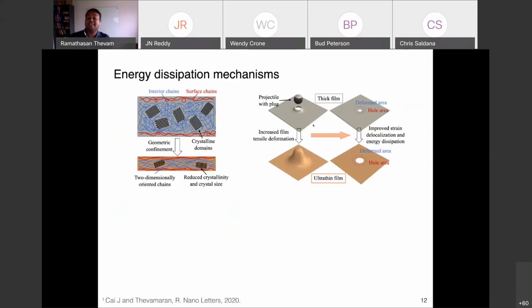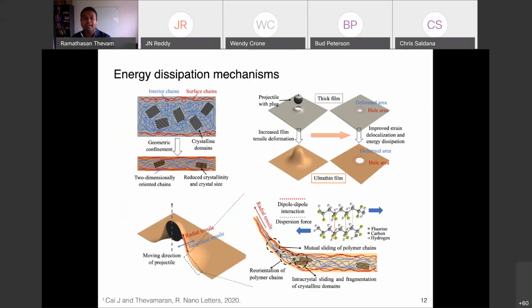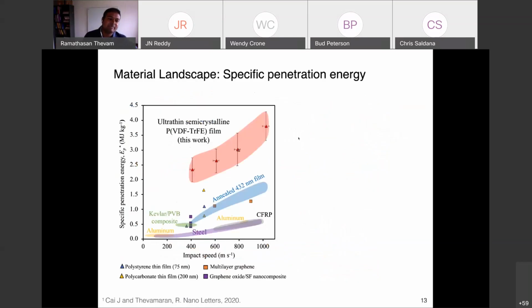So if you shoot, this is what happens. In a thicker film, it shows more of a brittle behavior, while the thinner film stretches, undergoes a large tensile deformation, and that leads to better energy dissipation. So what happens is, as you're stretching the film biaxially by the projectile, these crystalline domains fragment, and the polymer chains get stretched and flow into the deformation region, causing more mutual sliding between the polymers that can also engage piezoelectric effects. All these together have led to this increased specific penetration energy.